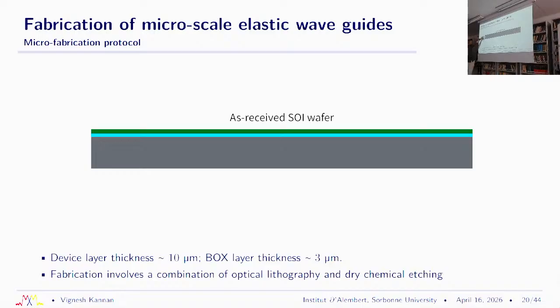So what we have here is a silicon on insulator wafer. That's what we call an SOI wafer. The SOI wafer has something like a 500 micron to a few millimeters thick base layer, which is a single crystal of silicon. We have an intermediate 2 to 3 micron thick layer, which is a buried oxide layer. In microelectronics, they call this the box layer, simply because it's buried oxide. It's a silicon dioxide layer in there. And on the top, you have a very thin layer, which is about 10 micrometers of single crystalline silicon, right? Now, I could make my device out of this really big block of silicon, but then I'll also be limited in the number of unit cells I can fit in there, because I have a fundamental limitation on the aspect ratio of my unit cell.